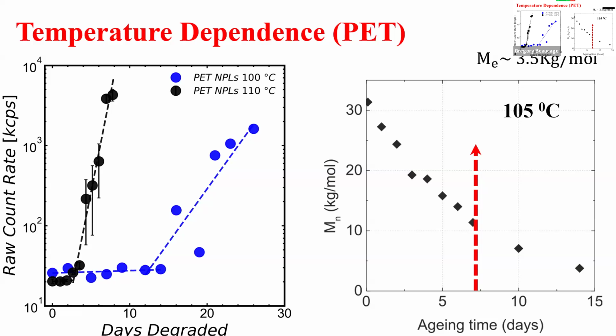This is kind of specific to PET, because it has ester reactions, right? It doesn't apply to polypropylene. Correct. But polypropylene has hydrogen abstraction reactions and other reactions. I don't care about the chemistry. I'm a physics person. The rates are going to be totally different, but the mechanism is what I'm caring about. It's not like I'm losing so much molecular weight that I'm dropping below the entanglement threshold and becoming brittle and creating micro nanoplastic. The mechanism cannot be embrittlement that way. It's embrittlement because of some other factor. And the idea I'm going to go back to is crystals being connected by amorphous phase.